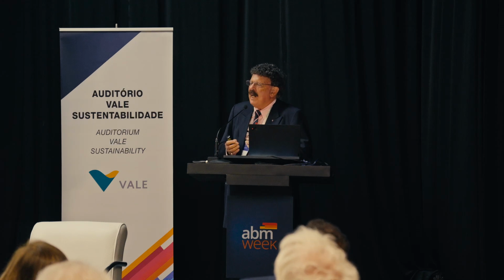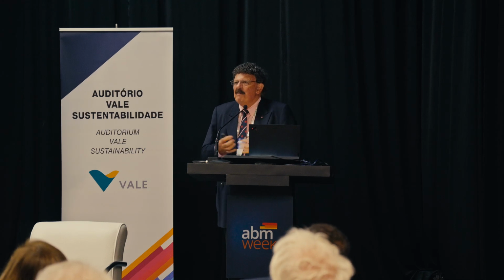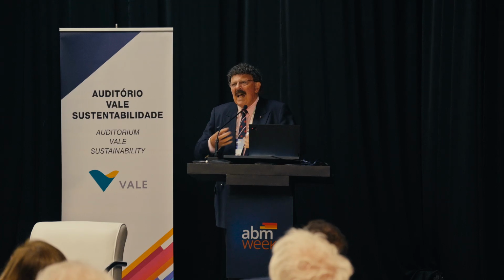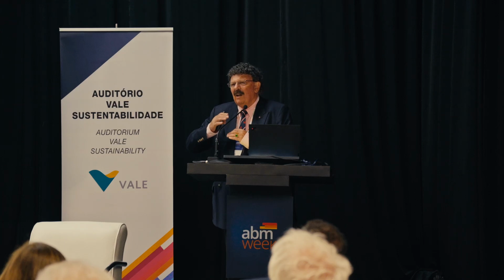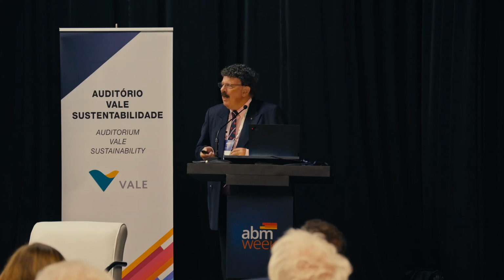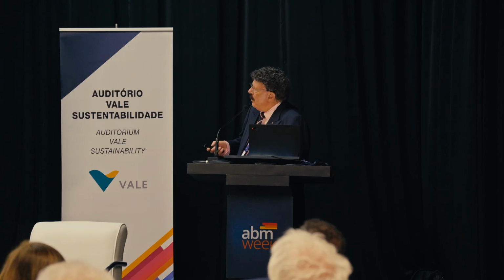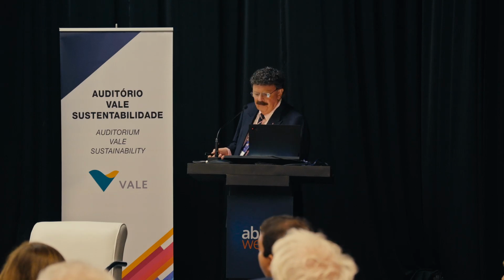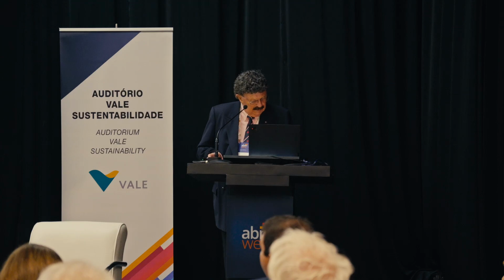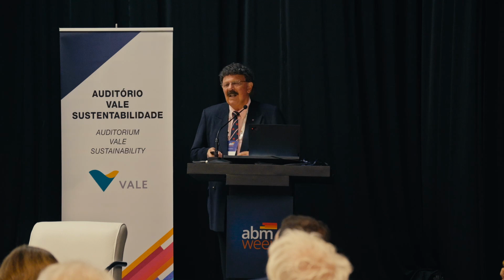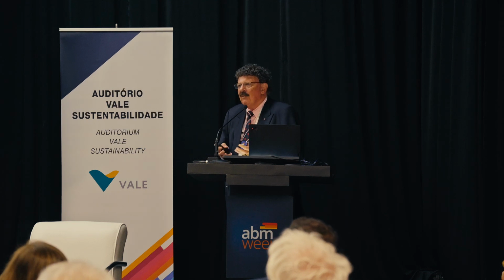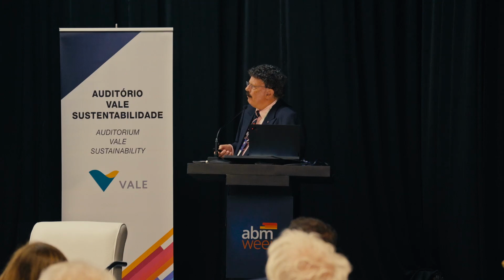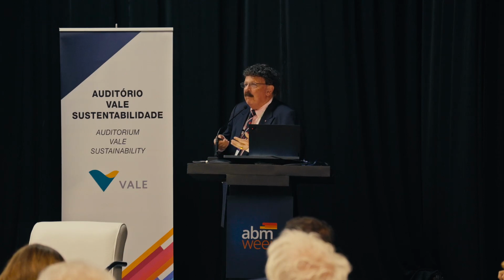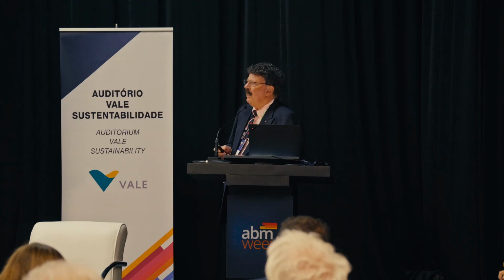This is associated, we think, particularly with grain boundary embrittlement and oxidation, and the lack of mechanisms to form dislocations. The ductile brittle transition temperatures are too high. But by adding group 4 elements, and the alloy we've been looking at is the niobium, titanium, tantalum, hafnium, we can get these additional deformation mechanisms, these difficult slip modes, and we can generate other mechanisms of plastic deformation, particularly kink band formation.